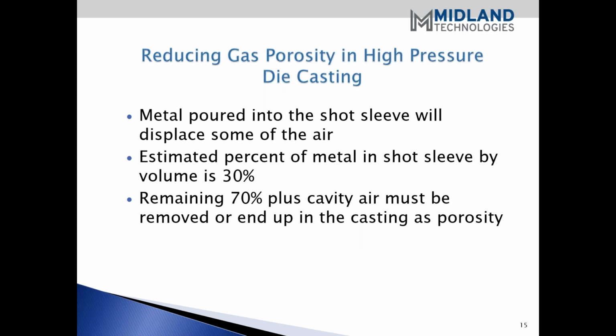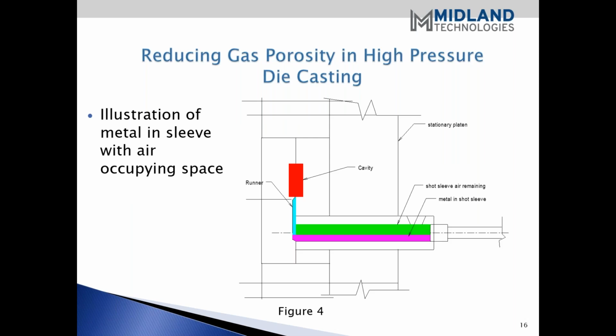Okay, so we pour the metal in the sleeve, and we displace a certain amount of air that's in the sleeve. That normally is about 30%. Now, it can vary by shot, but I would say in all my years of being involved with die casting and looking at different percentages in the shot sleeve, if you're at 30% full, you're pretty good. Which means that the remaining 70% of the shot sleeve consists of air. Next slide. So this is just denoting the air portion, the metal, and where we've got air in the system itself prior to injection. Next slide.